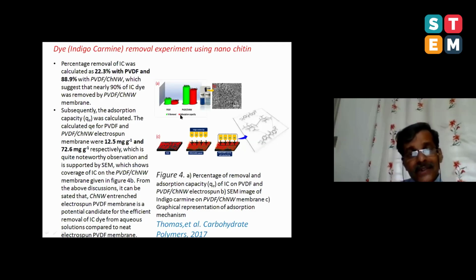I wanted to show you the result. If you use PVDF alone, look at this, this is PVDF alone. The dye removal efficiency is 22.3%. But if you combine PVDF with nanochitin, look at the dye removal. The dye removal efficiency is 88.9%. So by incorporating nanochitin into the electrospun PVDF system, my research group could make an excellent filter for removing indigo carmine dye from water.